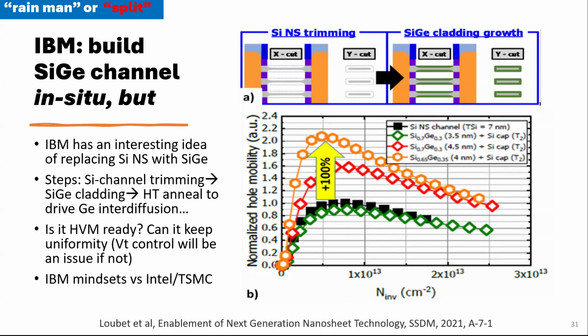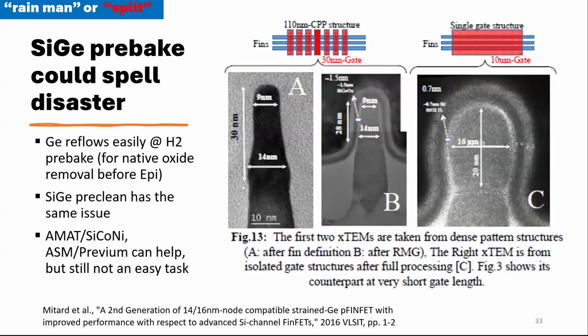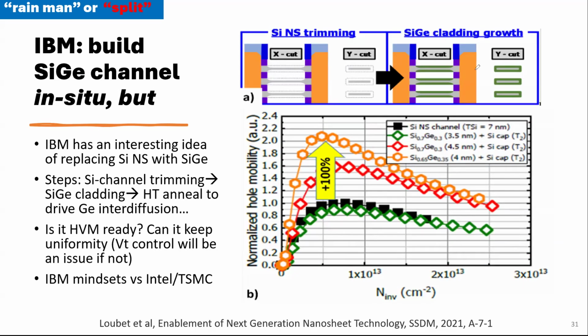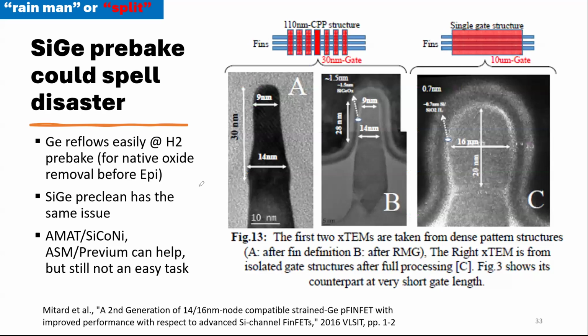On top of that, let's look at another concern. When you want to do cladding on top of here, you need to remove the native oxide out of the silicon, right? Use SiCoNi and something like that. And if you use too high a temperature, what happens? This is what happened if you use a high temperature anneal.